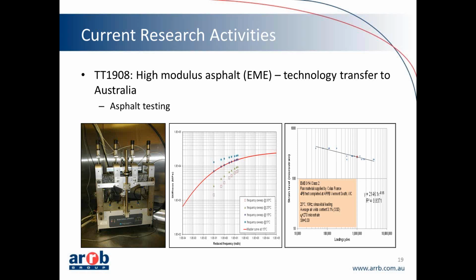Then the second element to the fatigue testing is to take 18 fatigue beams. So that's quite a substantial effort in manufacturing those 18 beams, and they're split up into 3 groups. So you have 6 for each subset, and they're tested at 3 different strain levels. And from that data, you can ascertain when the flexural stiffness has decreased to 50% of its initial value. Now, the Australian method only uses 3 beams and 1 strain level.